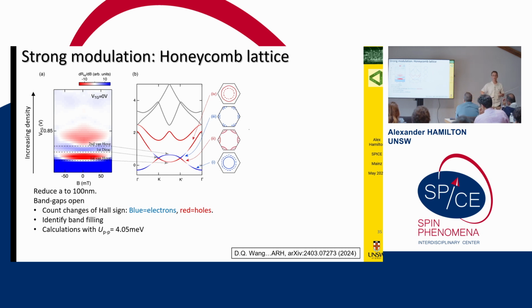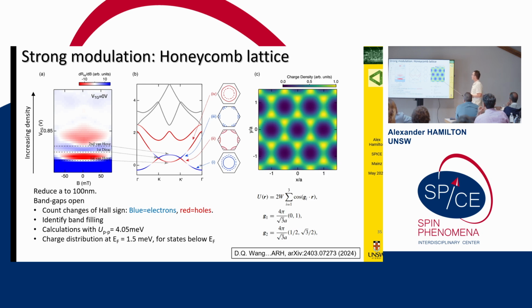So we can follow, in this artificial crystal, switching from electrons to holes and relate it directly to the calculated band structure. And the only parameter we have is the strength of the modulation potential. So that's really nice. We can calculate for that strength of the modulation potential what the electronic charge distribution looks like. And no surprise, it looks like a honeycomb lattice.